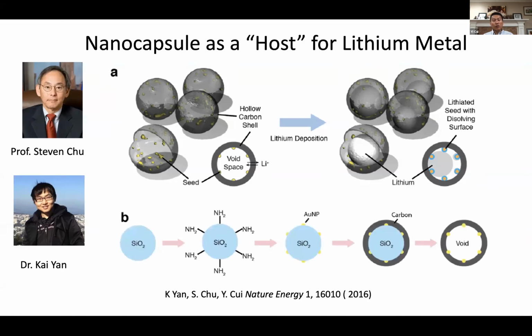So we made these structures using a templated method. Let me also mention, to make this carbon using a templated method, you don't want to have big pinholes in this hollow carbon sphere. Otherwise, the electrolyte is going to leak in and go inside. So you want those nanoscale pinholes. You can still etch away the silicon oxide template, and then this pinhole will be sealed once you form the SEI.